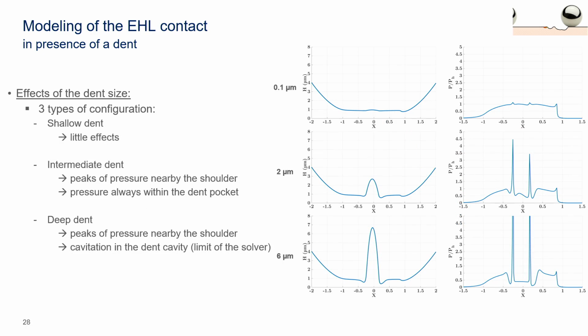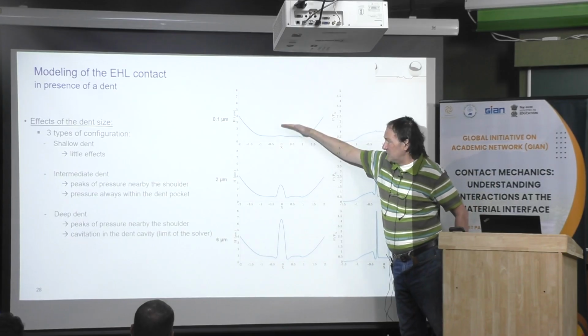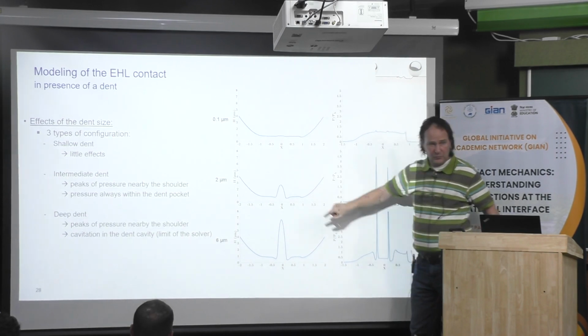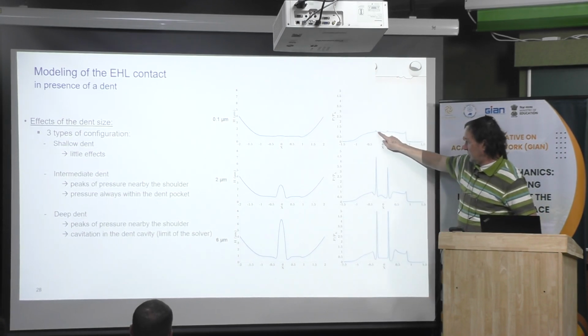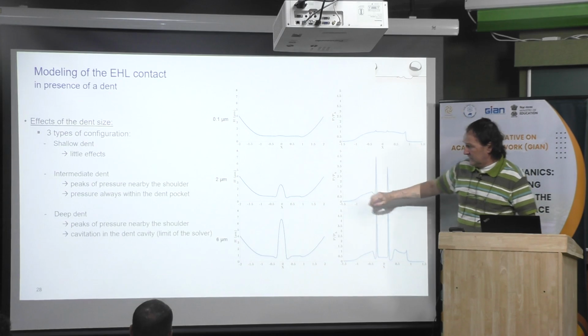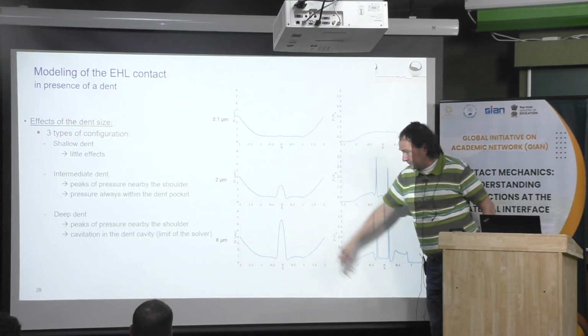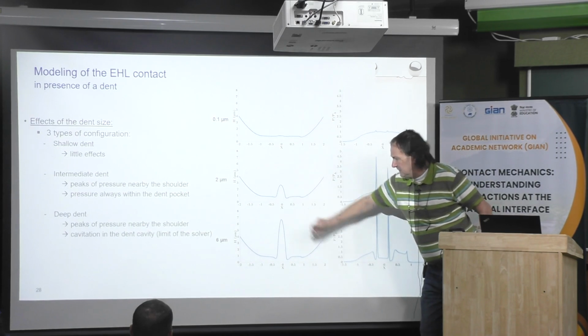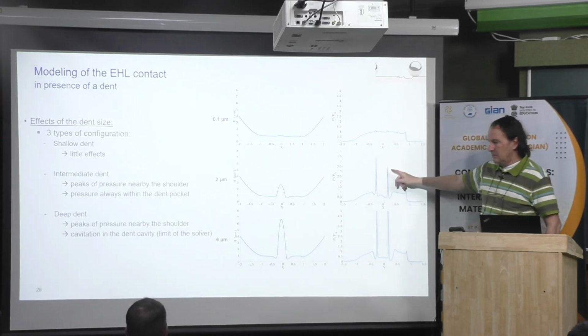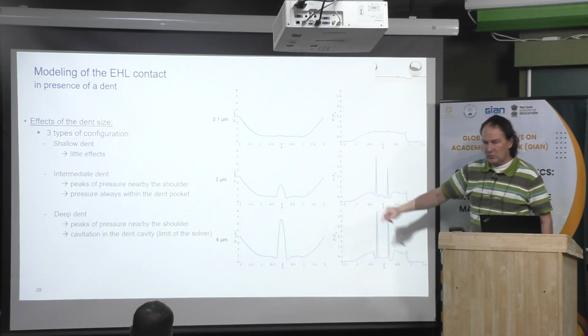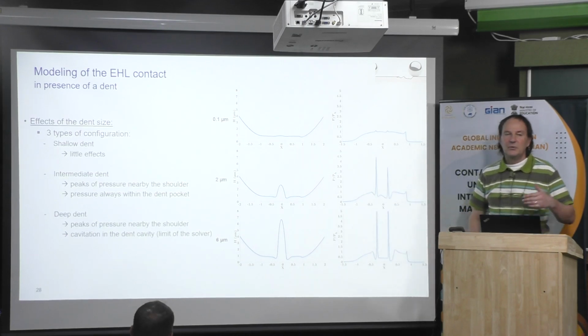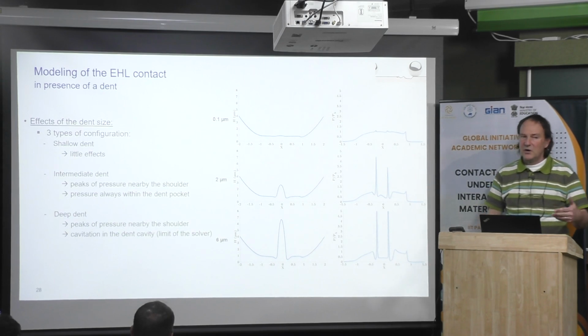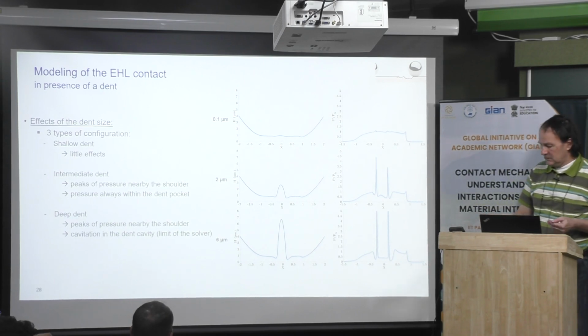Then this is more detail of what I said just before. You have here a dent which is very shallow, 0.1 micrometer. Then you can see on the deformed shape almost no residual dent. You can see the effect on the peak of pressure, which is very low. You can see something with a depth which is 2 micrometers. Then you still have a full film thickness here. You can see the peak of pressure on both sides. And this is something for 6 micrometers. Okay. Now there is no result for deeper dents because there is some cavitation and we are not sure about the quality of the solution.